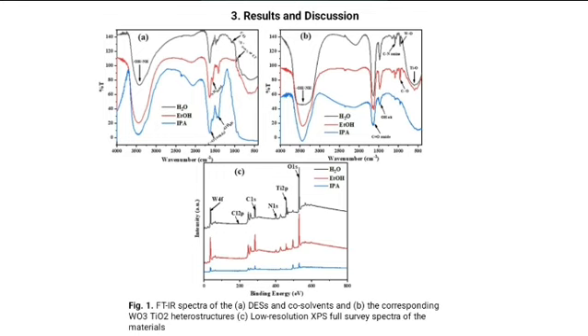Specifically, the broad OH to NH overlapping band was shifted to 3589 to 3291 wave number, with a very broad band for the water-based heterostructures, while these groups in the ethanol and the isopropyl alcohol-based compounds appeared at about 3447 wave number. The C double bond O band, due to the amide, was shifted to 1663 to 1634 wave number, while the alcoholic OH band, the amine C-N and the C-O vibrations were observed at 1473, 1162 to 1155 and 1087 wave number respectively.